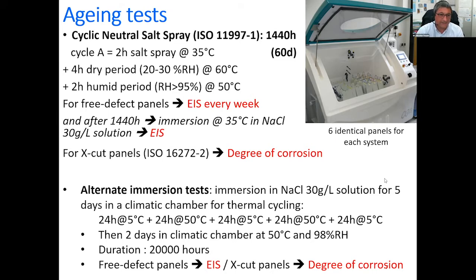And finally, we've got the alternate immersion test. It means immersion in a sodium chloride solution for 5 days in a climatic chamber for thermal cycling. It means 24 hours at 5 degrees C, then 1 day at 50 degrees C, 1 day at 5 degrees, 1 day at 50, and 1 day at 5 degrees C. And then 2 days in a climatic chamber at 50 degrees C and a relative humidity of 98%. We tested some free defect panels that were evaluated using EIS, and also X-cut panels that were evaluated using the degree of corrosion.